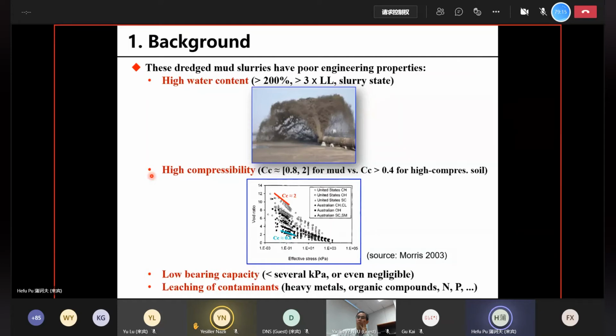very high compressibility. From the figure here, Professor Morris compiled lots of data for different kinds of dredged materials. We can see that the compression index, CC, usually ranges between 0.8 to about 2.0, and sometimes it's even higher than that. In contrast, in conventional soil mechanics, if the compression index CC is higher than 0.4, then we consider it as high compressibility soil. So you can see here the compressibility of mud slurry is usually at least 2 times that.